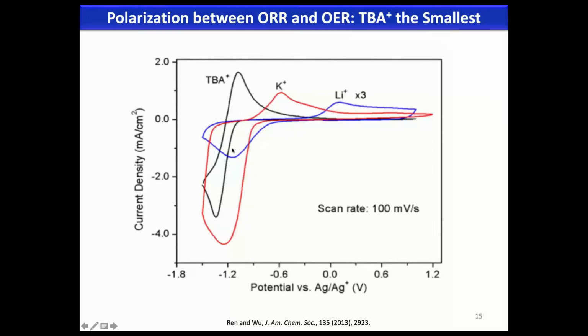And if you look at the polarization for lithium, this is something unbearable for industry. The polarization is over 1 volt. Think about energy efficiency, or round trip efficiency, it would be miserable. But if you look at potassium, it's much better. And we know potassium is a relatively soft metal ion in terms of polarizability. In the hard soft acid base series, the reduced species of oxygen is superoxide, O2 with a superscript minus. That is quite a soft base.